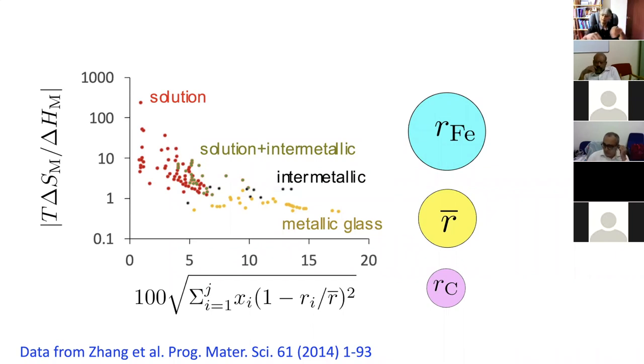But locally around misfitting atoms, you also have strains, and those are heterogeneous strains, and there are techniques to measure those strains. And they demonstrated experimentally that in the Cantor alloys, which I showed earlier, the level of strain is so small, the local heterogeneous strain around atoms is so small, that you can't distinguish it, for example, from pure nickel. Okay, so that doesn't really play a part in the Cantor type alloys, but many of the other alloys, for example, when we make the refractory high entropy alloys and so on, are likely to have much larger lattice strains due to misfit.